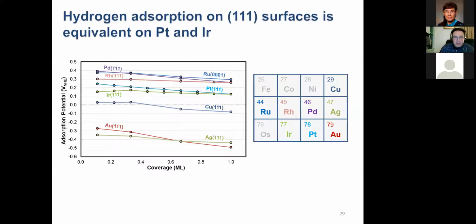So you can look at the coverage dependence of all these different metals, but if we zoom in here and here on platinum and iridium, we see that platinum 111 and iridium 111, and those were single crystal experiments, bind hydrogen about the same. So that must suggest that hydrogen adsorption energy is not going to predict why iridium is a faster catalyst in base than platinum.